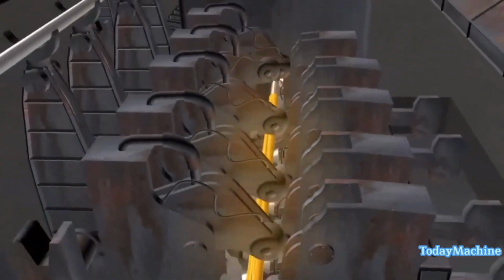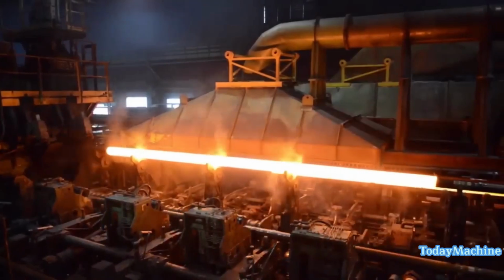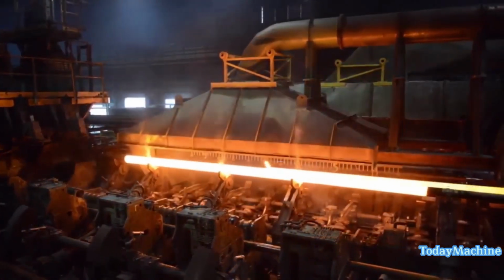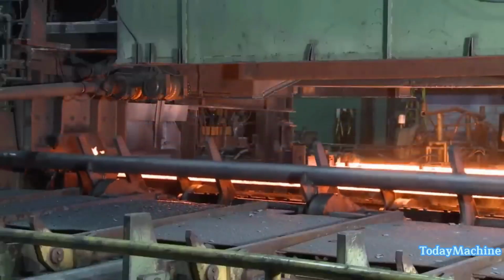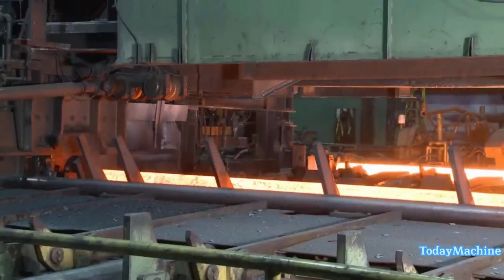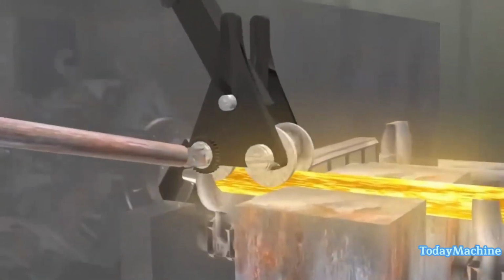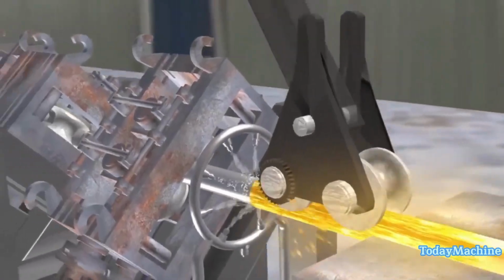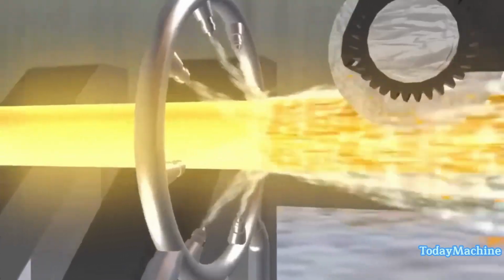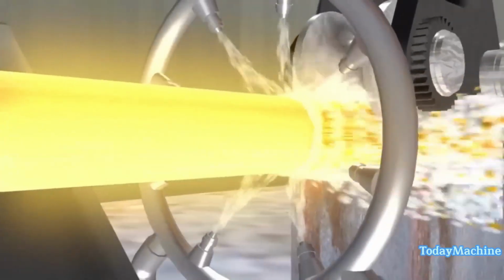At the rotary piercer, the solid round heated billet is converted into a hollow shell by cross-rolling over a high alloy piercing point. This cross-rolling action generates alternating tension and compression forces in the core of the billet, creating a void in the center as it comes into contact with the piercer point.